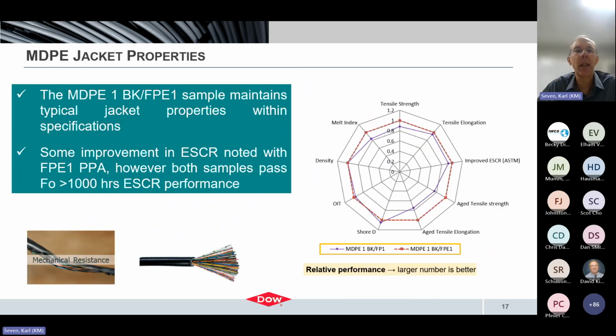Okay, I'm not going to spend a lot of time on this, but it shows that we did more extensive testing, given that we saw good performance with the polar polymer additive, to evaluate in particular heat aging and longer term aging performance of a compound with the polar polymer additive versus a compound formulated with a typical fluoropolymer additive. Overall, we achieve basically similar performance, and we can still meet all of the typical jacketing property requirements for medium density jacket. In particular, the aging performance, and there were other properties that I don't show here, electrical properties and so forth, where we were also similar overall in performance.